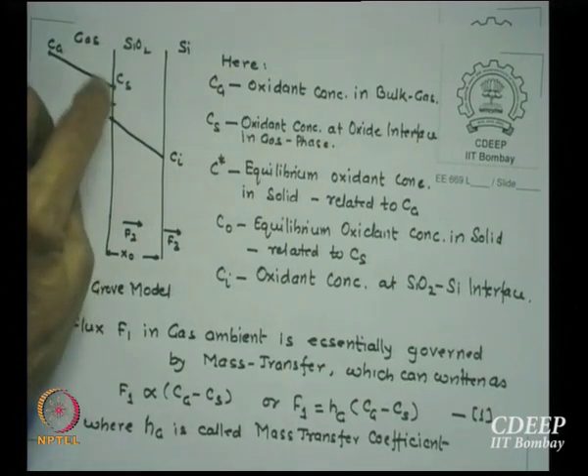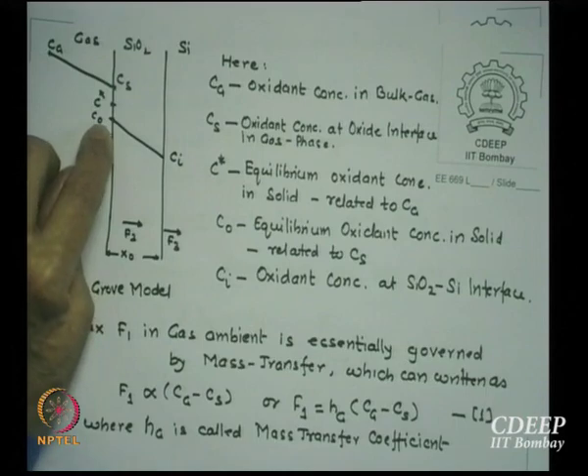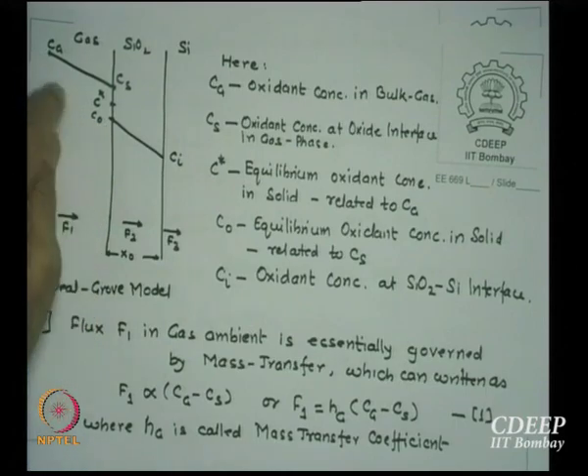Cs is available, which corresponds to C0 in solid. I just now said the gas concentration and the equivalent solid concentration are related through the mass transfer coefficient, and through that to partial pressure, through that to Henry's constant, to the actual concentrations. So the gas is coming. Equivalently, how much gas is available overall, of which how much will diffuse from the surface is C0.